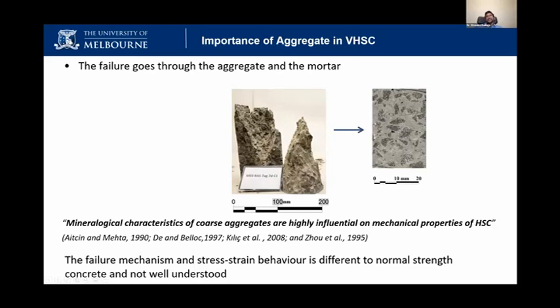For example, if you see these pictures, this concrete sample's strength is more than 100 megapascal. But you will clearly see there's a difference in failure compared to normal high strength concrete. If you look close up, you can see how the aggregate is crushed. In normal strength concrete, usually the failure goes around the aggregates. The ITZ is very weak in normal strength concrete because of the higher water to binder ratio.